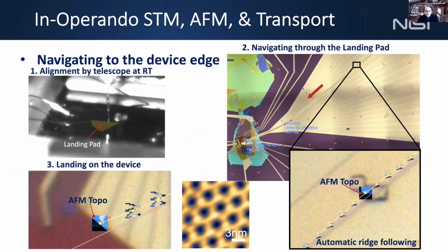Now, in this particular sample, when you get to the graphene area, the first thing we noticed is that the STM measurements show that it has a Moiré superlattice. This is an STM image. The larger lattice here is the Moiré superlattice of 3.5 nanometers, and you can see the graphene lattice superimposed. So we already know we have new physics, or different physics, coming into play. When you have a Moiré superlattice like this, you break the AB lattice symmetry, and that's going to already give us a zero field gap. So we're going to start out with that Landau level 0 already being gapped at 0 field. The degeneracy is already lifted due to this Moiré superlattice. So that's important to know.